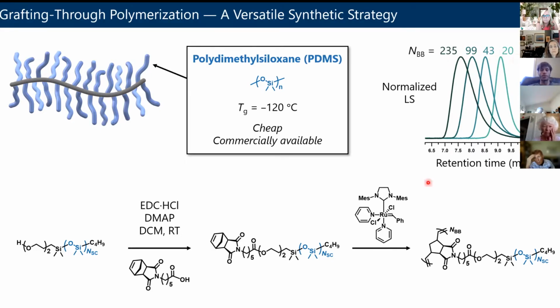It turns out by the ratio of the macromonomer, so the PDMS with the norbornene, relative to the catalyst, because this is what's called a controlled polymerization. So the details of that aren't so important, other than to appreciate the size of these molecules. If you look at the picture in the upper left, we start with PDMS chains that are of order 5,000 or 10,000 grams per mole, and they have that reactive norbornene on the end.